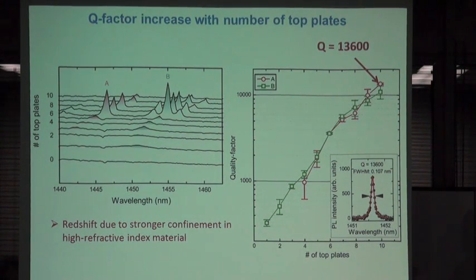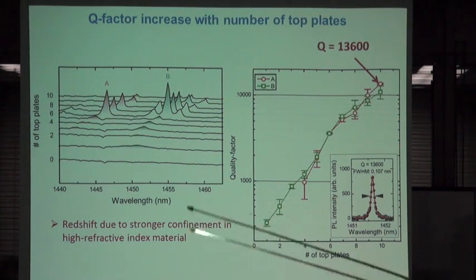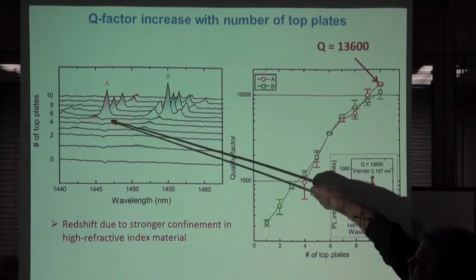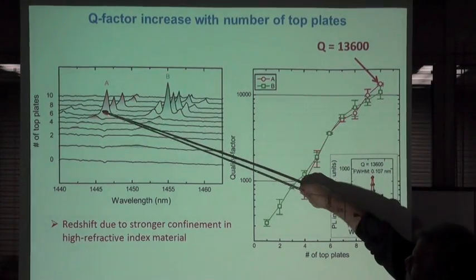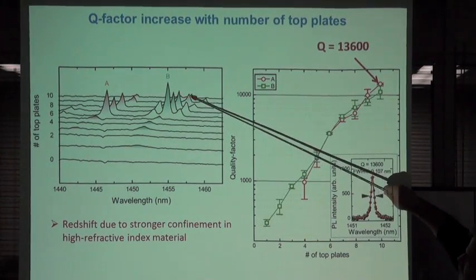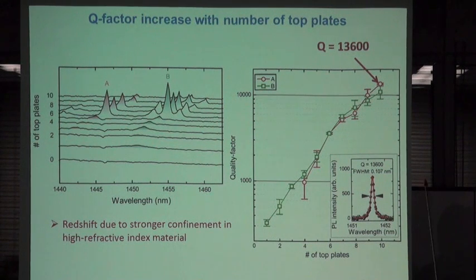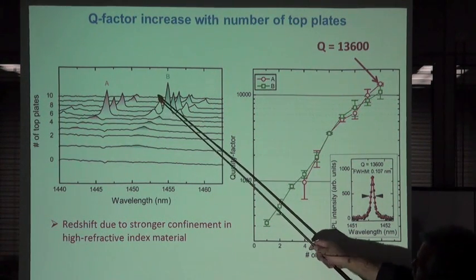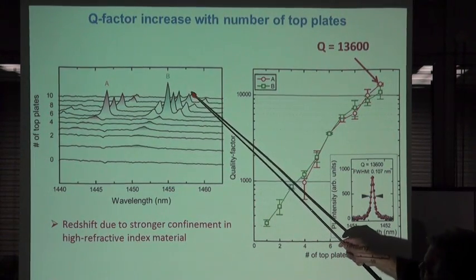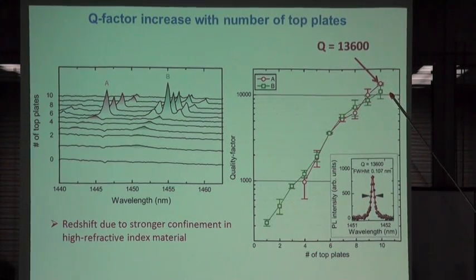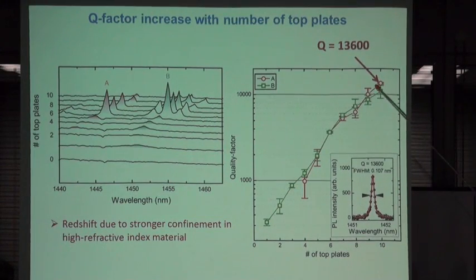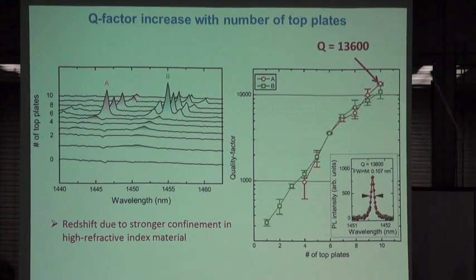We have only the stack below, and then we add 1 plate after the other and measure the luminescence, and then you see how these modes are coming up, and then these are very strong here, and then they are decaying again in intensity because light is not coming out anymore. Because if I have more plates on top, I confine the light inside, and the light cannot be extracted anymore. But if you look at the Q factors, these last modes here have the highest Q factor. So the Q factor is just increasing up to more than 10,000 here.